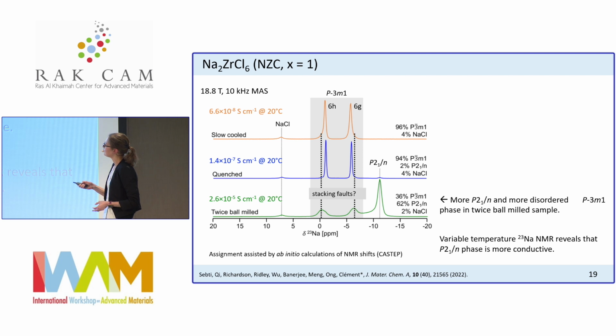But what's important to remember here is understanding what this does to conductivity. The conductivity of the slow-cooled phase is very low, but it increases by almost 3 orders of magnitude if you ball mill again. And so the next question was, if the conductivity is going up, is it because we are inducing more and more disorder in the P-bar-3m1 phase, or is it because we are forming this new polymorph of NZC? Here we did some variable temperature NMR experiments, which I'm not showing here, but basically the main result was that this P21/n phase is the one that's responsible for conductivity in this material.